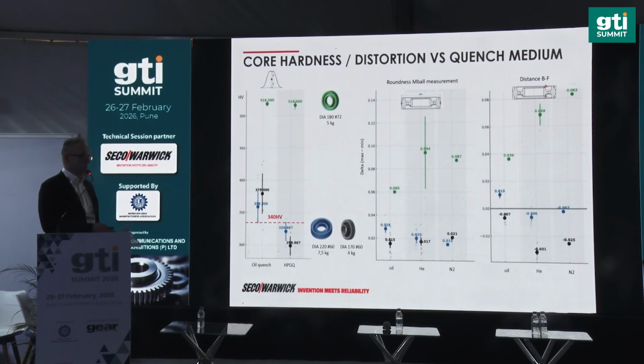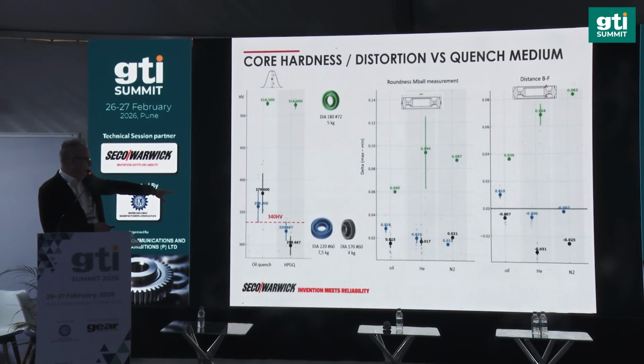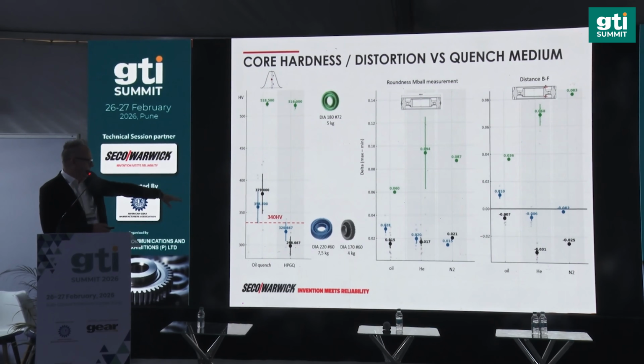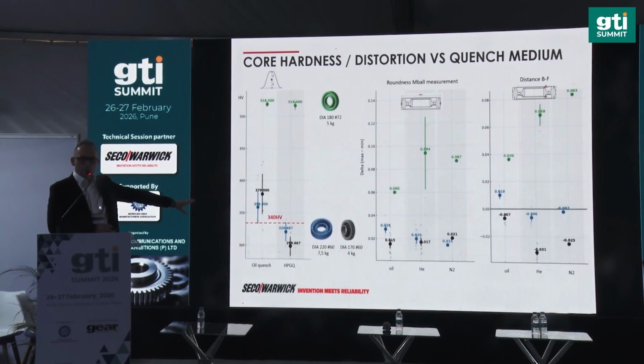And if the requirements are set relatively higher than typical ones, as in the picture here, where the requirement for core hardness was 340 HV, and for gears of diameter 220 millimeters, 170 millimeters, of a weight of 7.5 and 4 kilograms, high pressure gas quenching was not able to meet those requirements. Therefore, oil quenching was the only solution that could be applied.